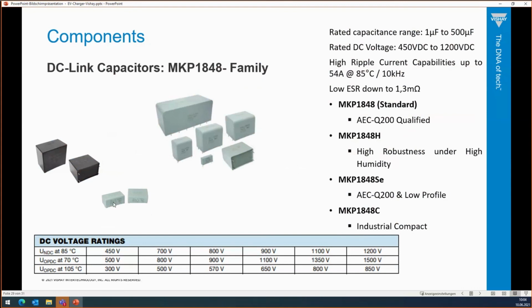For the DC-link capacitors, we have made a lot of experience since the last 10, 15 years that we are on the market with the MKP 1848. We are expanding the portfolio to have higher robustness against humidity. We have automotive, slim versions. We have compact versions. This is just data sheet stuff, but what is important and what is not visible at first sight, we qualify our parts at 85 degrees C. So that means a 700 volt capacitor from Vishay is an 800 volt capacitor from competition. Because some of our competitors rate their caps at 70 degrees C. So it's